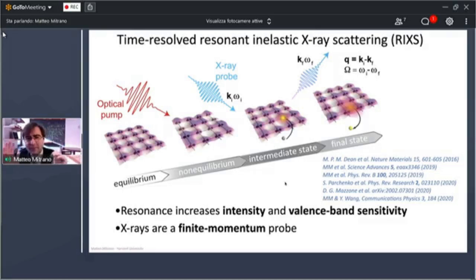Polytechnic in Milan. And essentially, in the non-equilibrium incarnation of this technique, we can follow the dynamics of a material that is driven out of equilibrium with an optical pump, and then probed with X-ray pulses with a certain momentum and a certain energy that excite core states into the valence states, and then we de-excite by emitting a photon with a certain momentum kf and a certain energy omega f. The difference in momentum and energy tells you about the nature of the excitations in the driven state.